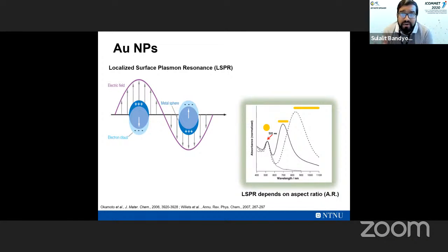If you have a small aspect ratio nanorod, as we call them, they're very good for photothermal therapy, which means that you shine in light, it absorbs the light and produces heat, and that heat can be used to kill cells. On the other hand, if there are large structures, the larger nanorods, they are super useful because of their scattering properties in optical imaging. So you can use them as contrast agents to view inside the cell much better than you could do without a contrast agent.